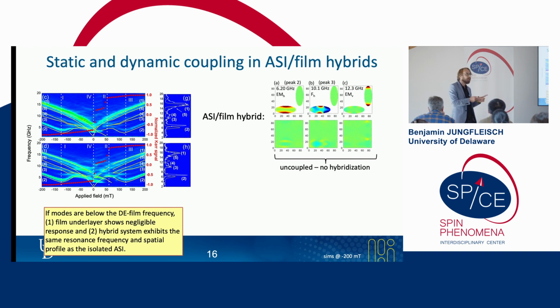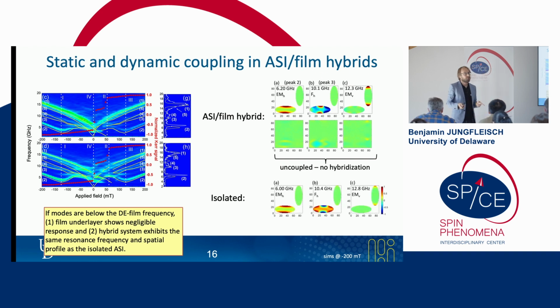And if we compare now the dynamics in the artificial spin-ice system in the hybrid system with that of the artificial spin ice that is isolated, we see that the hybrid system exhibits the same resonance frequency and spatial profile as the isolated artificial spin-ice system. So if you just take a look here, this is peak 2 in the hybrid system, which corresponds to the isolated artificial spin-ice system here, the same for the other modes. So it's as if the film was not there.